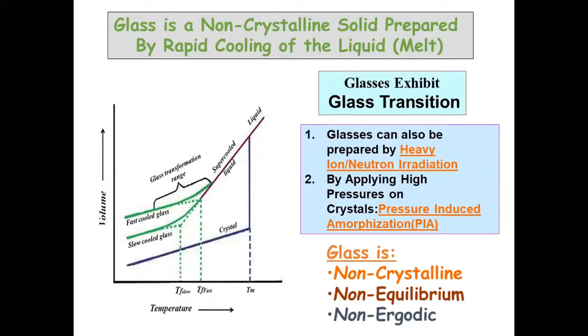So this is a very well-known diagram between volume versus temperature. Temperature along the x-axis, volume along the y-axis, and you start with some liquid like molten silicon dioxide or molten B2O3. For example, the melting point of silicon dioxide is around 1400 or 1500 degrees Celsius. If you cool your silicon dioxide melt very slowly, maybe at a rate of 1 degree Celsius per hour, then at some particular temperature, which is known as the melting temperature or freezing temperature, the volume will decrease abruptly. You will see an abrupt change in volume, and you get a crystalline phase.